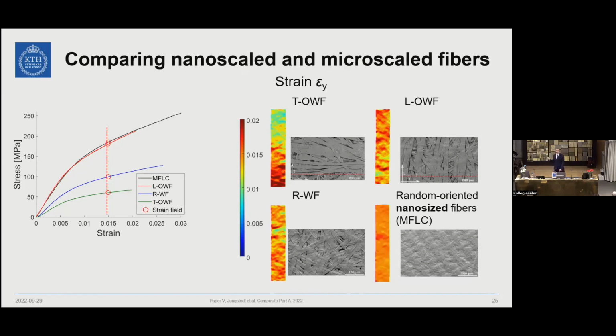Now we can also compare this by disintegrating the fibers even further, so we get a finer structure with nano-sized fibers. So these are micro-sized and these are nano-sized. And then we can see that we are actually reducing the inhomogeneity of this composite. However, in the longitudinal direction for this material, we have quite similar behavior, although the nano-sized fibers have a higher strength.